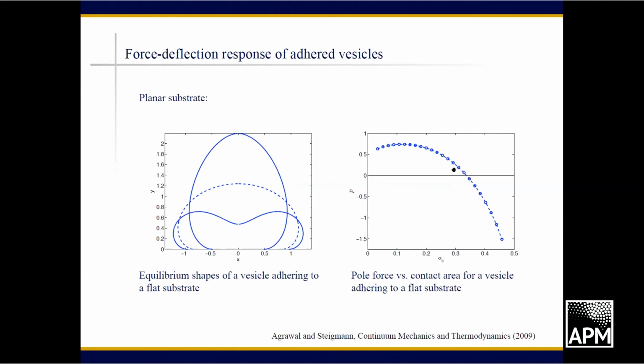And then as we transition to positive point forces, we have a deformation like so. What we compute is that there is a maximum to the point load associated with any area. So naturally, as we pull up on the bilayer, the contact area decreases. That there's a maximum load in equilibrium. So if we attempt to impose a larger load than this maximum, there will be no equilibrium state, and there